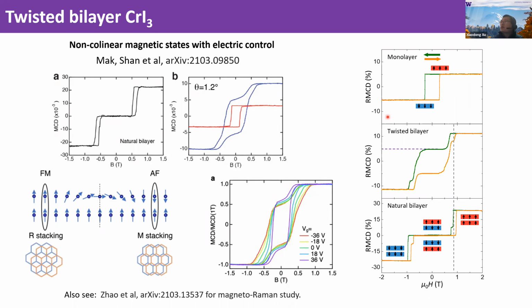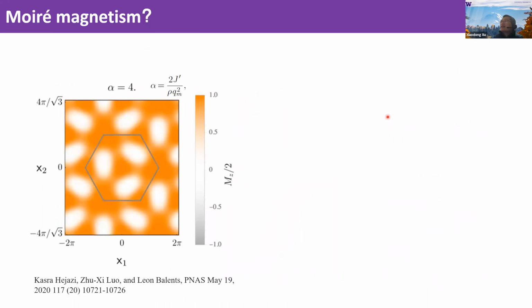But the question is, what type of magnetic ground states do we have, right? There are already a couple of theory works that discussed the magnetic patterns for these twisted bilayer CrI3. They call them Moiré magnetisms. The image I show you here is from Leon Balents' work, who calculated the magnetic patterns in small angle twisted chromium triiodide. You can see that the orange part represents the strong magnetization, and it's a ferromagnet. And in the white part, which is zero magnetization, it's an antiferromagnet.